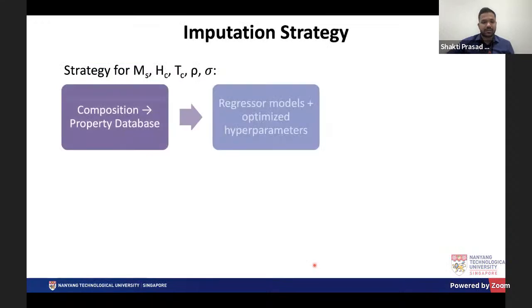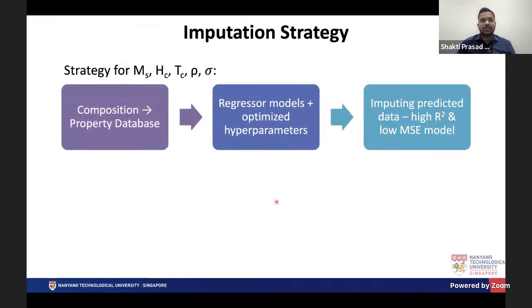Finally, once we have done the data cleaning and extraction, we have a pre-processed database which can now be used for predictions. As I said, this data was collected from literature sources, so it has a lot of heterogeneity in it. From one source we get the mechanical properties, but from another source we get the magnetic properties. For many of the materials we don't have mechanical, magnetic, and electrical properties all together. We have very few sources for that. So there was a huge amount of missing data inside the database. In order to tackle that problem, a strategy was developed.